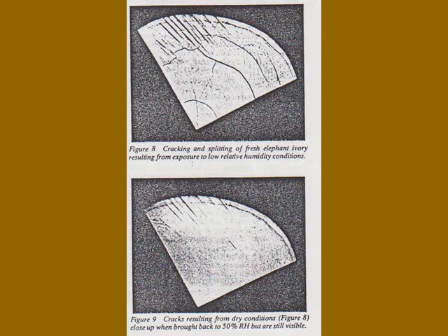To reduce inherent brittleness, researchers impregnated ivory with plasticizers. This actually worked to improve the plasticity of ivory, but had adverse effects aesthetically in the form of discoloration. Because of unsatisfactory trial results, this methodology was abandoned in favor of simply employing moisture barriers to minimize hygroscopic action. The researchers studied several moisture barrier coatings and found that Saran 150, a polyvinylidene chloride latex emulsion, aka PVDC, was particularly effective when applied to various types of ivory. Unfortunately, this emulsion is prone to visible yellowing in as little as 5 years.